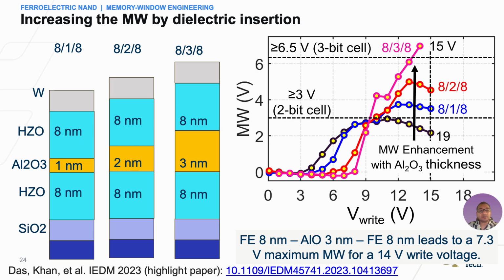We then increase the aluminum oxide insert thickness from 1 to 3 nanometers while keeping each HZO layer at 8 nanometers. The 838 structure produces the largest result, a 7.3 volt maximum memory window at a 14 volt write pulse. That exceeds the 6.5 volt target while keeping the full ferroelectric plus the dielectric thickness at 19 nanometers.